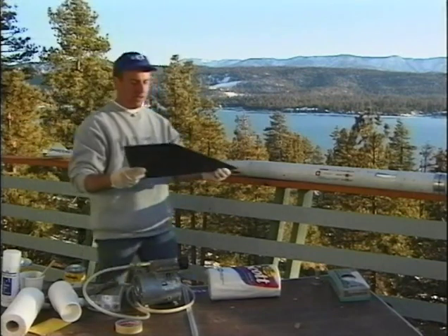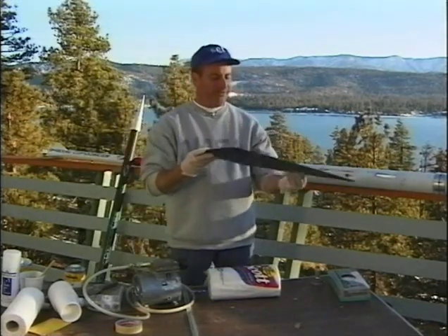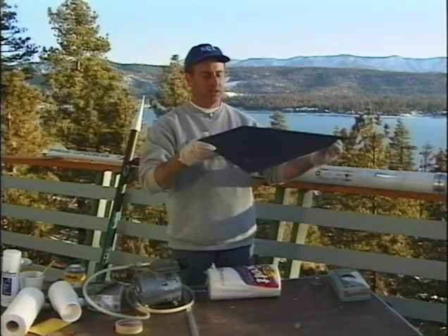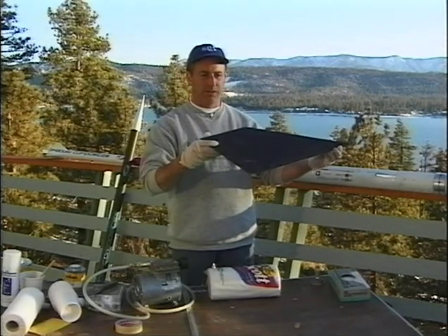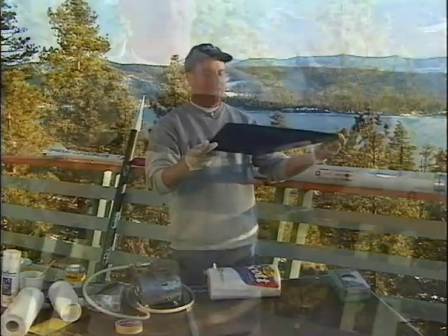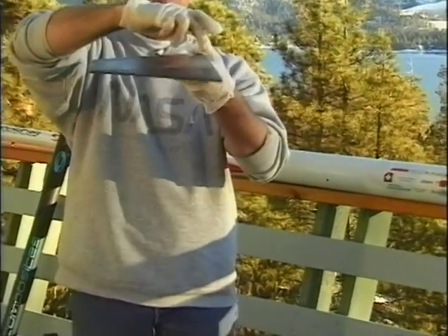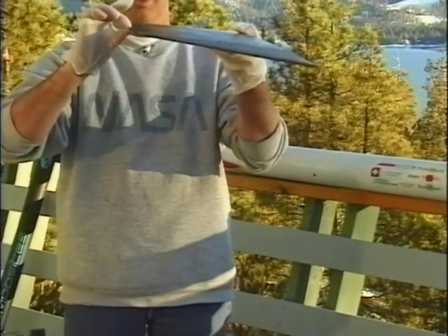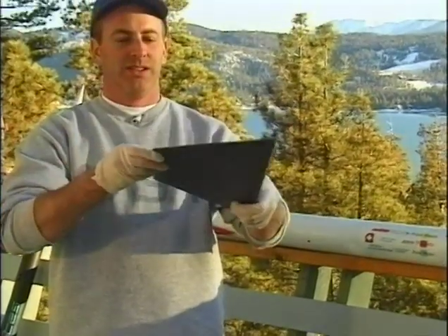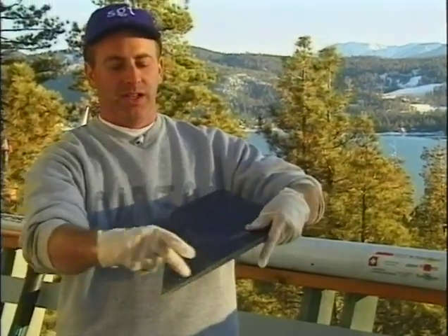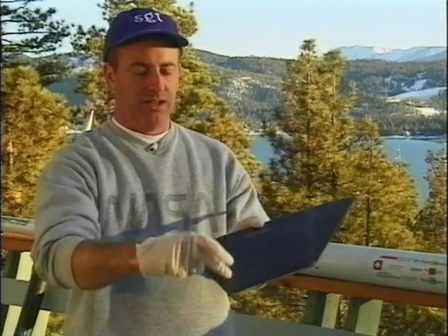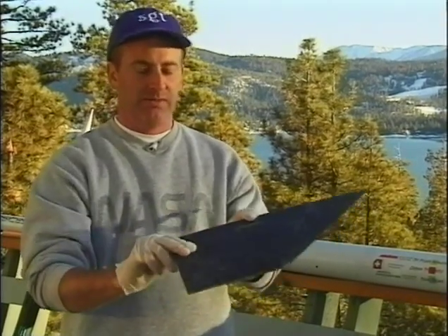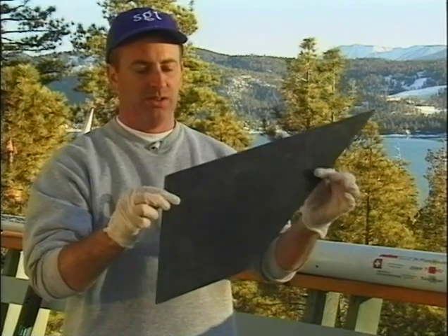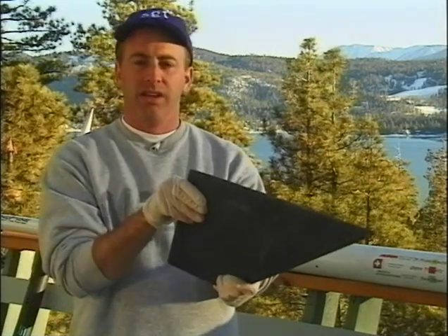This is the finished result. This is a full-scale Astra BD fin executed in carbon fiber, both sides. It's got a taper from 0.4 of an inch at the root down to 1/8 of an inch at the tip. It's also got bevels running at the forward extent and the aft extent of the fin. A fairly complex fin shape, but they're two sides taken using the technique that I just showed and then bonded together.